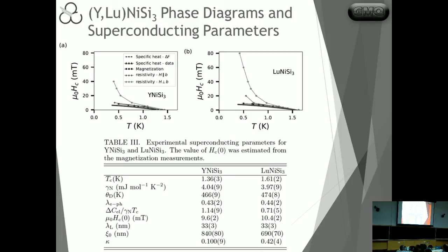Superconductivity is killed with very low fields, except when we apply the resistivity perpendicular to the b-axis. Then for some reason also we are not killing the superconductivity as fast as with the other ones, which is also worth looking at. From all of the superconducting parameters, we can see from, for example, the coupling parameter here, that these are in the weak coupling regime. As I said, here we can see that they are really type 1 superconductors with low kappa values, and so on.